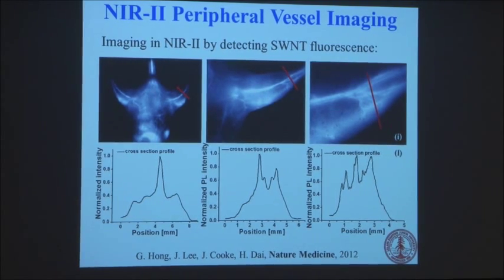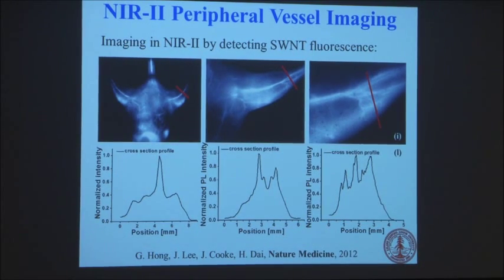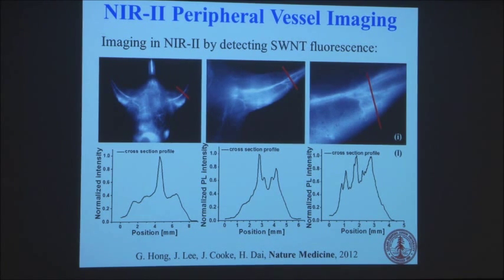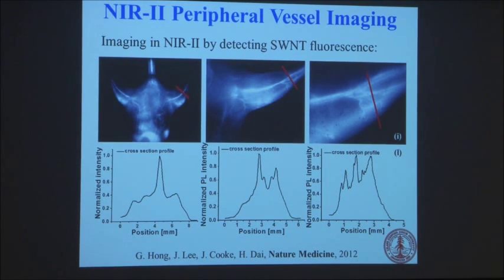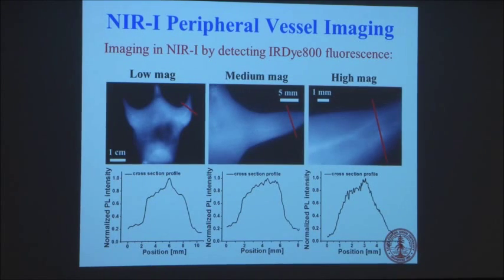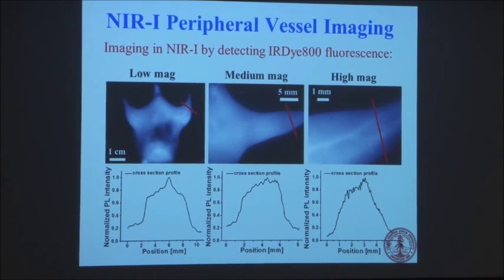And you can see the vessels very well, okay? And the smallest vessel we can see from these profiles is about 30 microns, okay? And these vessels are about 1 to 3 millimeters deep from the skin. Okay, so this is now a big difference in terms of what you can do with optical imaging, okay, of animal models.